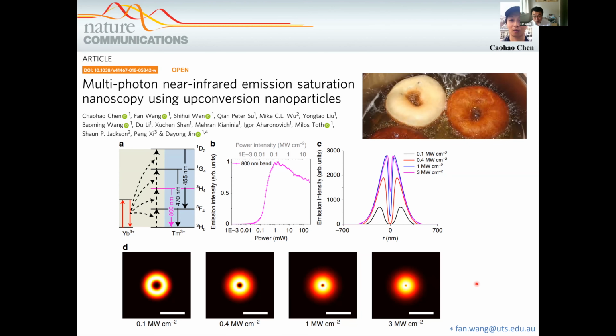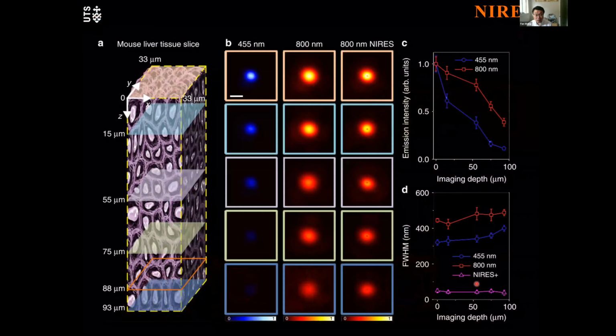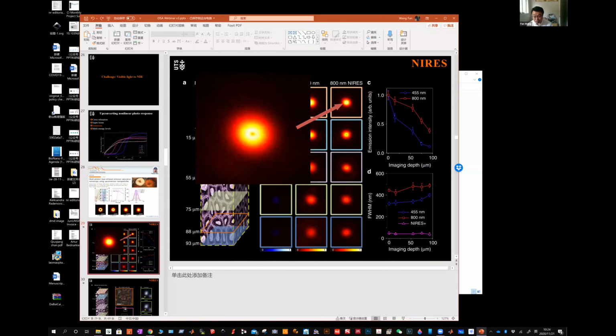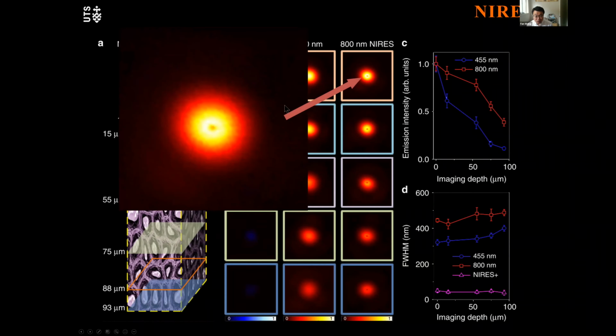And so this gave you super resolution information. And we tried to put this particle inside a deep tissue, like 90 micrometer tissue. And we can see that for the blue light almost fade off, but the 800 emission will keep here. And if we just use a donut beam, you can see there's a small hole in the middle, probably too small for you to see. So you see that there's one hole in the middle.